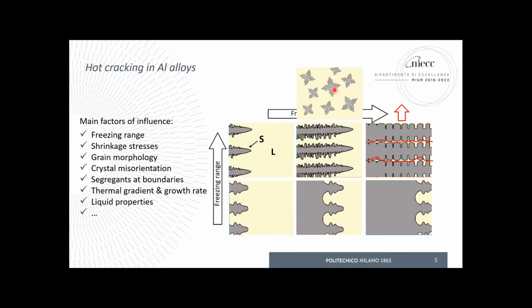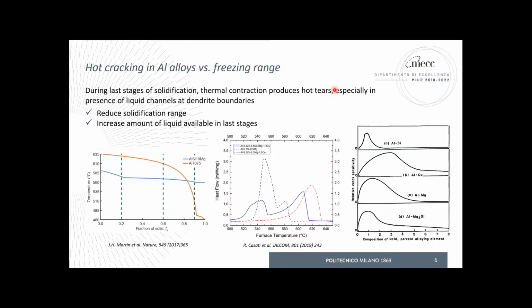In the following of my presentation, I will try to give you some suggestions about what we can do for the design of high-strength aluminum alloys, trying to avoid this kind of cracking problem we have to face. So the first one was to manipulate somehow the freezing range of alloys. Indeed, looking at the plot here on the left-hand side, we realize very easily that those alloys that have a very flat, let's say, solidification curve in the very last stage of the process.